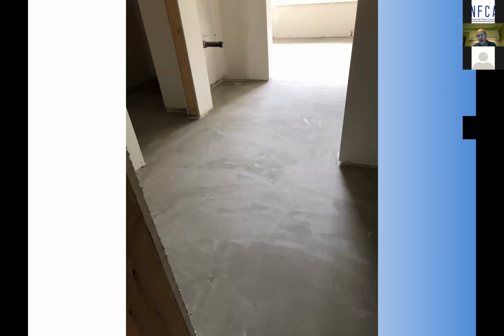You can patch over top of it. This is a bit of a rough first coat on here, but you can patch over it. And there are some instructions that your manufacturers would give you on timing for getting on it. Like in this case, there's a window where we try to get on as soon as it dries to the touch, within a couple hours, and do our patching so that we get good mechanical adhesion to it.